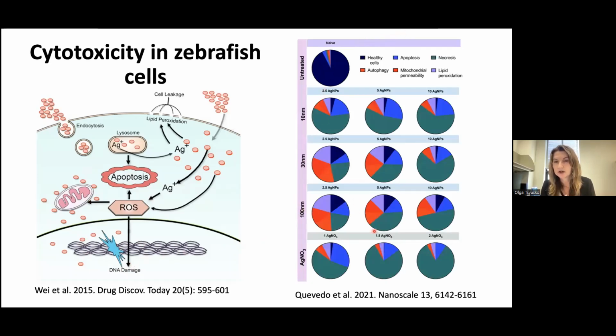And in this diagram, you can also see, in zebrafish cells, the different toxic effects for different sizes and different concentrations of particles. At the bottom, you can see those toxic effects separated for silver nitrate. If you compare the silver nitrate distribution of toxic effects with the toxic effects in response to the smallest nanoparticles, in this case 10 nanometer silver nanoparticles, there are a lot of similarities. A huge proportion is taken by necrosis. There are hardly any healthy cells left, and as we increase concentrations, those healthy cells are completely eliminated. However, with increased size, the distribution is different. We still see a lot of toxicity, but it's different from silver nitrate.